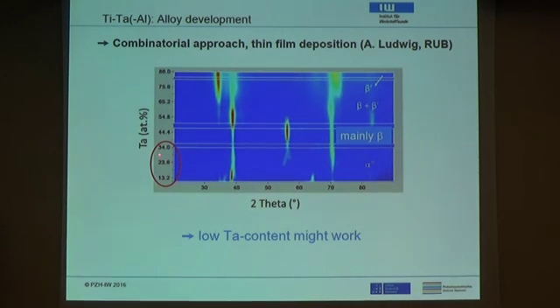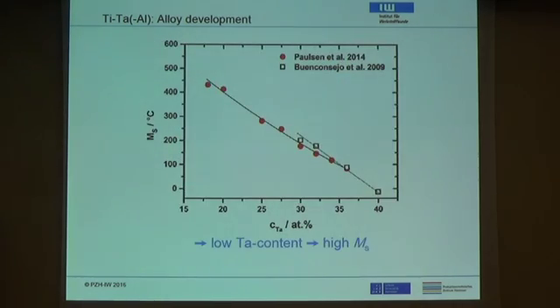Here you see the tantalum content, and this here is 2 theta from an X-ray study. And then normal material has a composition of 30% tantalum. And here you see the martensite peaks. And interestingly, when he lowered the tantalum content, those martensite peaks were still present. So based on this work, we thought, okay, maybe low tantalum content materials do work as well. So we did cast some bulk materials. And actually that's what we got.